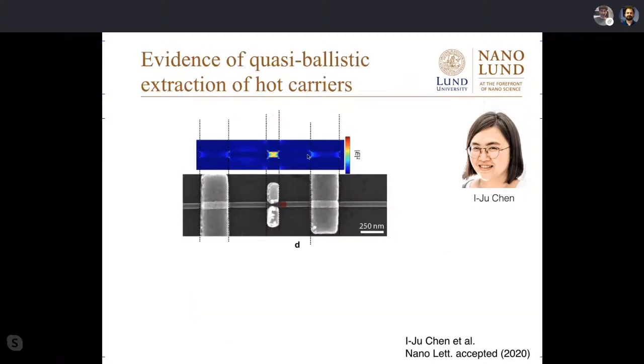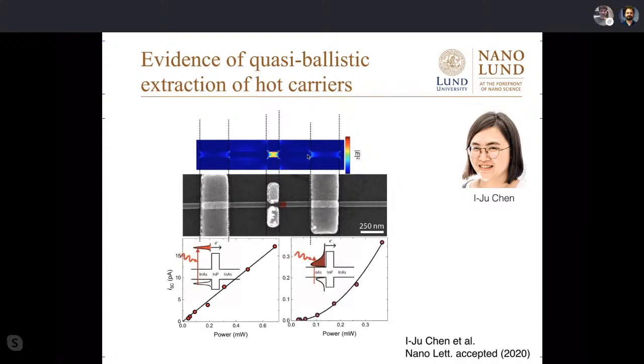And she did that here. She showed very nicely that she can actually absorb light in this way. She did the same experiment before and after putting on the plasmonic element, so that's very nice. But the other very cool thing she did then was to play with the light wavelength she uses. So she can either use a light wavelength that would put electrons above the barrier, where they in principle can ballistically, without any thermionics, just fly across the barrier. Or she can use a light wavelength that puts electrons into the conduction band and heats the electrons in the conduction band, but relies on thermal emission through that thermal tail here.